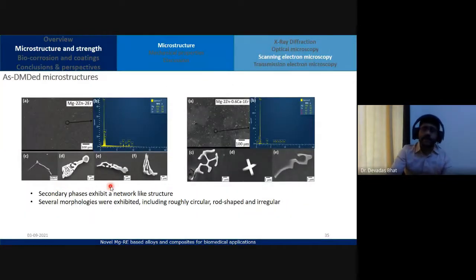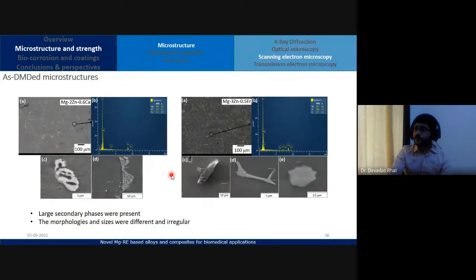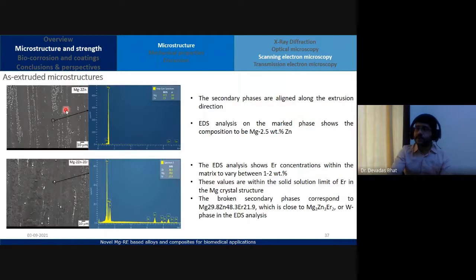This is the SEM and the EDS images, wherein you get information about different phases and the morphology of the secondary phases. These are for the as-DMD microstructures, and for the as-extruded ones, you can see here the secondary phases are nicely elongated along the extrusion direction.